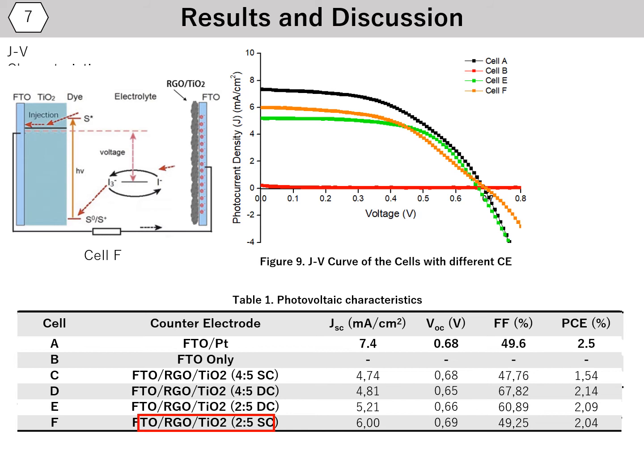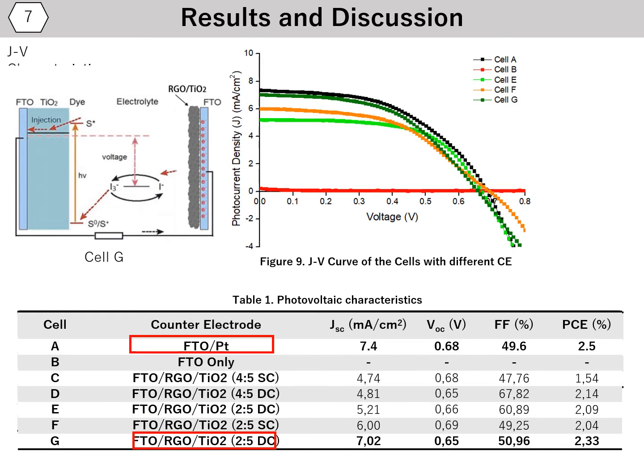However, the current density and efficiency of the cell are still lower than using platinum counter electrode. Last, with the cell using RGO titanium dioxide composite in ratio 2 to 5 with optimum thickness, we obtain its photovoltaic characteristic emerge with almost similar cell performance as cell A. However, this measurement result shows that this RGO titanium dioxide composite electrode has catalytic activity for redox couple of iodide triiodide electrolyte as effective as the platinum counter electrode.